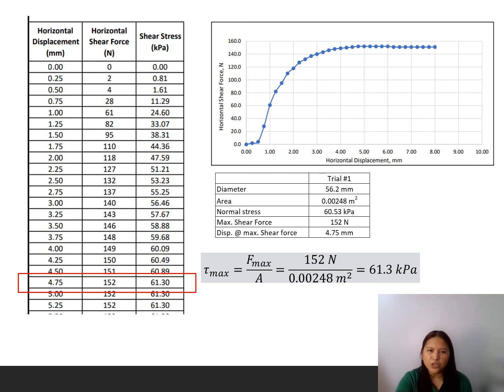The direct shear apparatus used in the study is strain-controlled. In a strain-controlled test, a constant rate of shear displacement is applied to one half of the box. The resisting force, shear force of the soil, corresponding to any shear displacement, is measured. The table and graph show the resulting shear force for any given horizontal displacement. Note that as the displacement is increased, as expected, the horizontal force also increases. But after the displacement of around 4.75 millimeters, the shear force is maintained at 152 newtons. This therefore corresponds to the maximum shear force, and we can now calculate the maximum shear stress as shown. For this trial, we therefore have a maximum stress of 61.3 kilopascals.